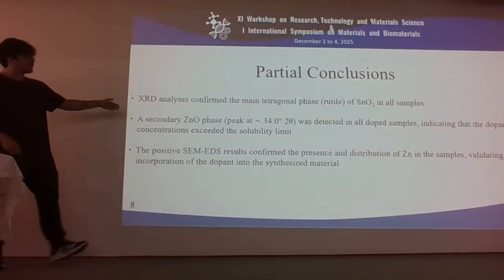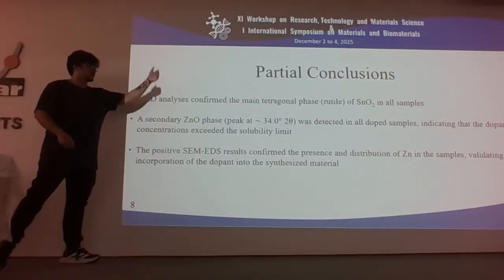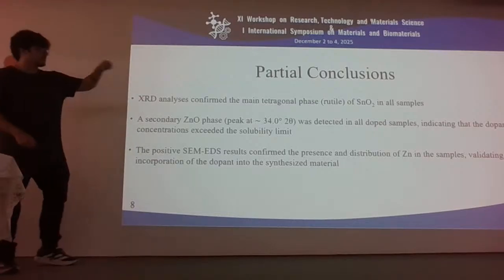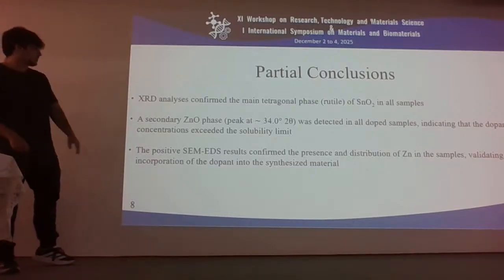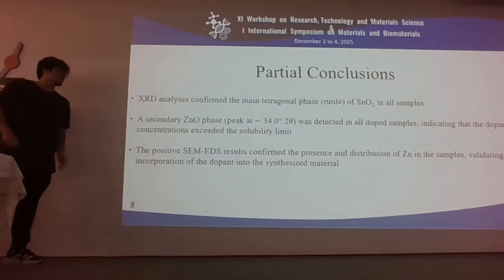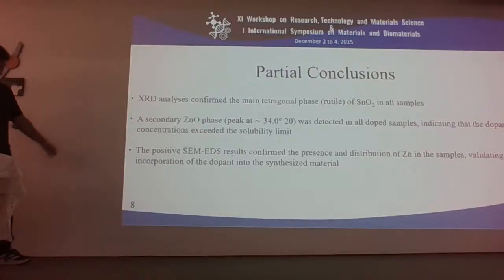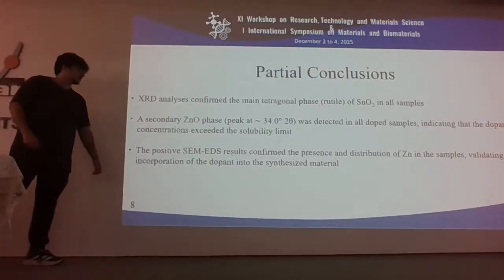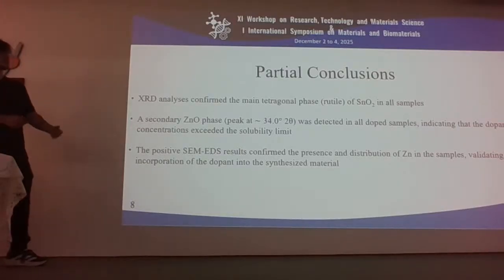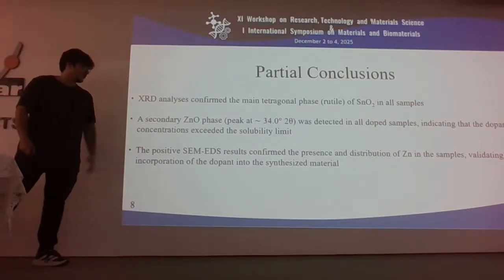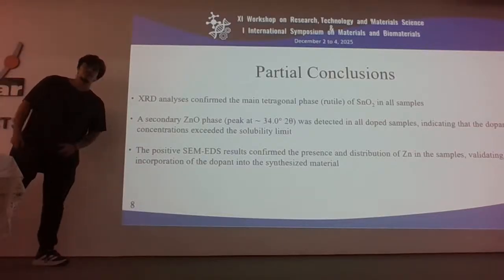So our partial conclusions: the XRD analysis confirmed the tetragonal phase (rutile) of the SnO2 samples, and the secondary phase, the peak more to the right, was detected in all dopants, indicating dopant concentrations exceeding the solubility limit. The positive EDS results confirm the presence and distribution of Zn in all samples, validating the incorporation of the dopant into the synthesized material.